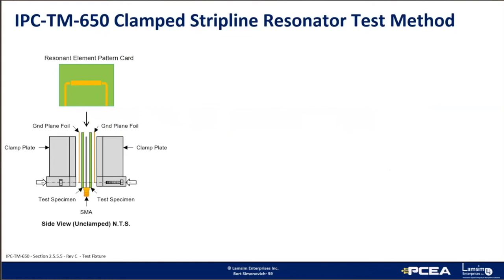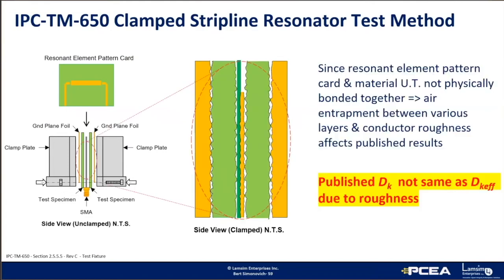Since this method only assures consistency and quality of a product, it does not guarantee the values will directly correspond to design applications. Published Dk/Df tables are not the same as the effective Dk due to roughness. This is a key point to keep in mind, and here's why. Because the resonant element pattern card and the material under test are not physically bonded together, air is entrapped due to the roughness of the various constituents shown here. And as a result, the published Dk is not the same as the effective Dk due to the roughness.